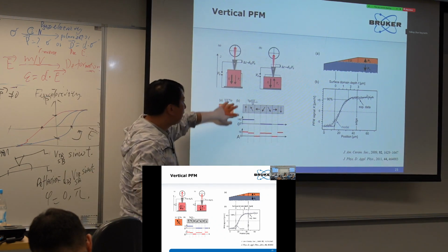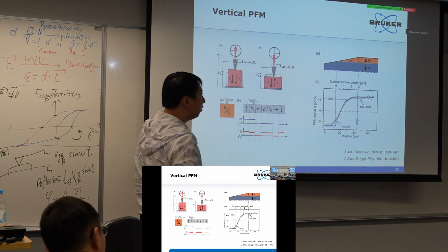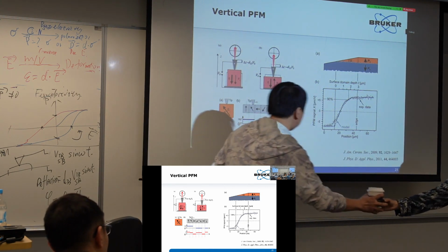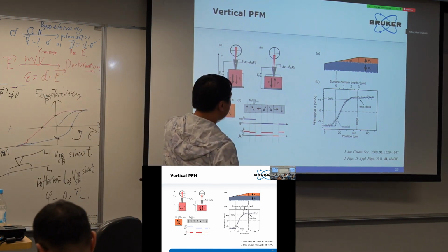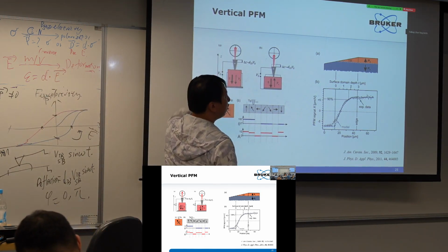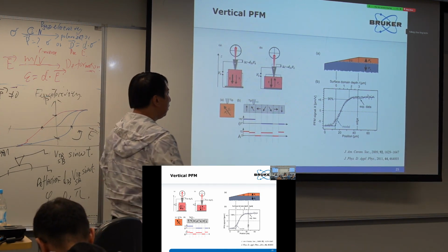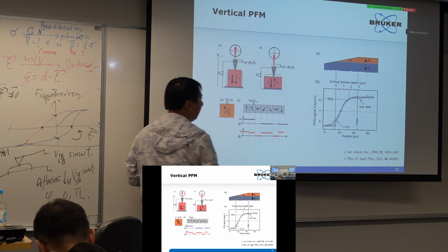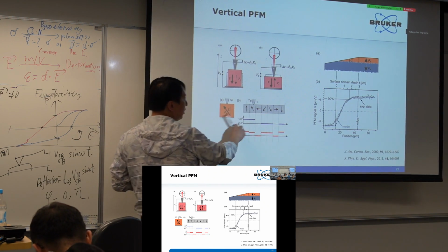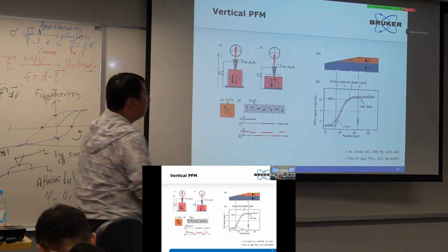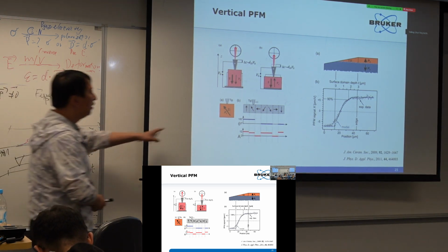And then about the phase, because we only study the z components, it has only two directions: one following our electric field, or opposite to our electric field. So the phase has only two values, 0 or pi, and the amplitude can change due to the orientation of our polarizations.